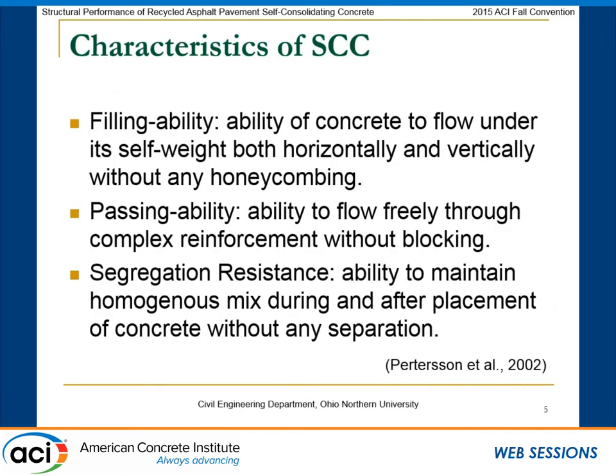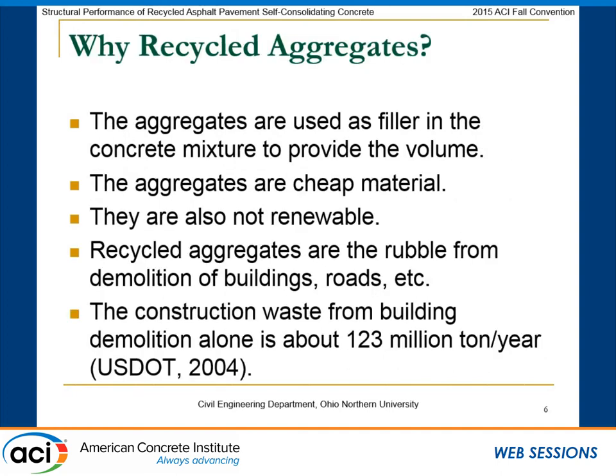Some of the important characteristics that we look for in self-consolidated concrete: we want to make sure that we have filling ability, so that the concrete can spread vertically and horizontally, and we don't have any honeycomb problem. Passing ability, we want to make sure that the concrete does not have blocking from the reinforcement. And segregation, we want to make sure that we have high resistance against segregation for SCC. We incorporated the recycled aggregate, which is the recycled asphalt pavement, in this research.